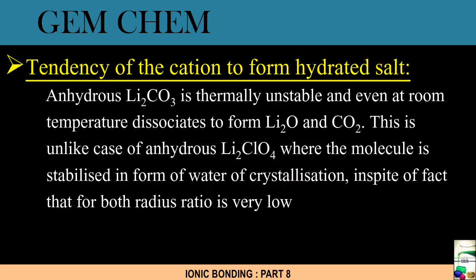Why is this so? If you see here in lithium carbonate, the radius of Li+ is much less than the radius of carbonate. There will be inefficient packing in the crystal lattice, right? And the lattice will be unstable, which is already being seen. For this reason, the small Li+ can readily polarize this CO3 2- radical, weakening the carbon-oxygen bond. Hence, this causes the rupture of one of the carbon-oxygen bonds in the carbonate and thus the formation of these two.